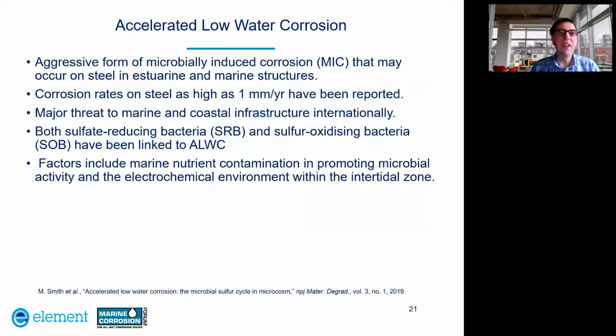So I now want to look at another example or case study, which is accelerated low water corrosion. This is an aggressive form of microbially induced corrosion, or MIC, that may occur on steel in estuarine and marine structures. Corrosion rates on steel as high as 1 millimetre a year have been reported, and it is a major threat to marine and coastal infrastructure internationally. Both sulfate reducing bacteria, or SRB, and sulfur oxidizing bacteria, SOB, have been linked to this form of accelerated low water corrosion. The factors to consider include marine nutrient contamination in promoting microbial activity, and the electrochemical environment within this intertidal zone.